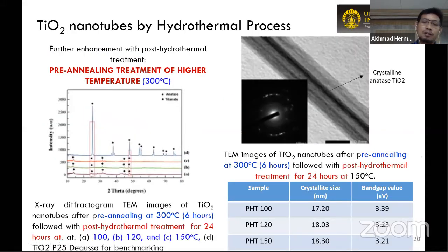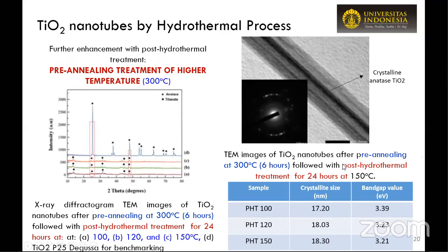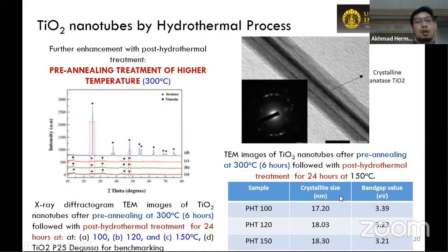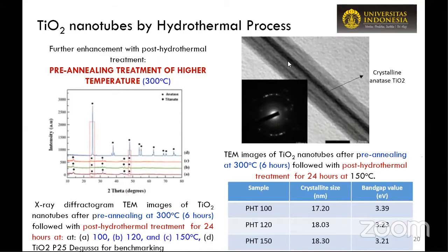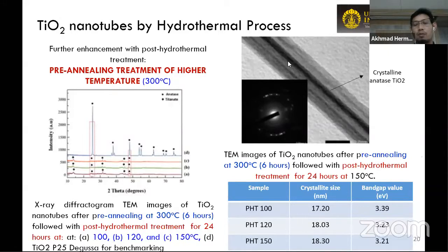Further, we tried to modify the pre-annealing temperature. Previously, we subjected the samples to pre-annealing at 150 degrees Celsius, but now we raised it to 300 degrees Celsius. We can see that the result is much more promising, for the band gap energy of samples with post-hydrothermal treatment at 100, 120 and 150 degrees Celsius. The band gap energy can be reduced further to 3.39 and finally 3.21. So it is getting closer to the inherent band gap energy of anatase, which is 3.2.